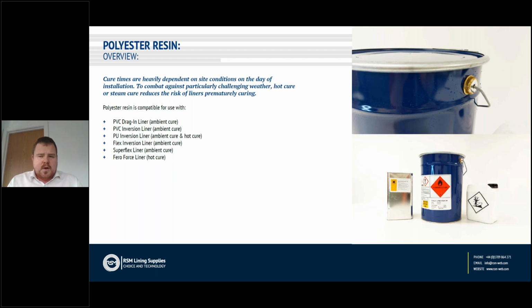To give you an overview of the hot cure and ambient cure process using polyester resin, we can use polyester resin with most of our cured in place pipe liner reinforcements. In terms of the felt liners, ambient cure can be used with the whole range of drag and inversion liners from Applied Felts and through ourselves, with flex inversion liners and superflex for going around 90-degree bends or for lining down downspouts. And using the hot cure process, we can also utilize polyester resin with our ferroforce liner.